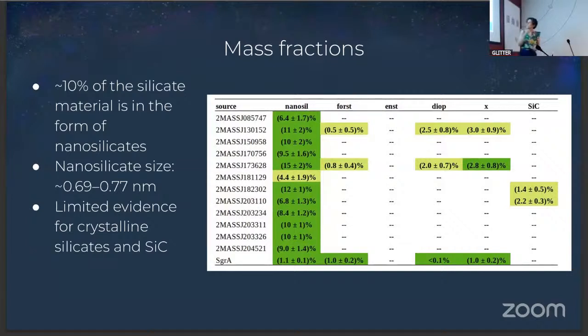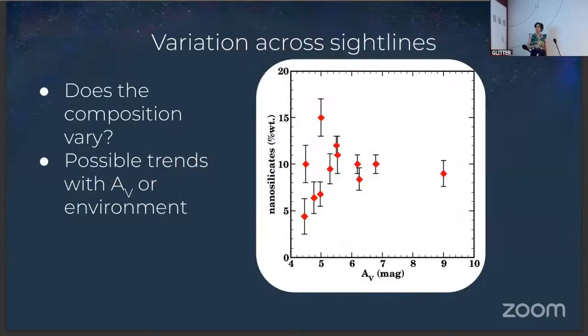Right. So, okay, so that's the main result. The other result is that we were able to constrain the nanosilicate size because remember that was a free parameter, and we find that it's around 0.7 nanometers. Right. So we looked at the nanosilicate fraction, the weight percentage in nanosilicates as a function of extinction. We do not find any correlation in that. So this is a plot that is also going to go in the paper, but we do not find that there is a strong trend with that.